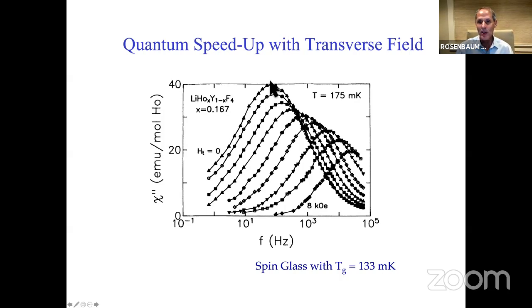Now, as I put on the transverse field, and this is 8 kilogauss of transverse field, the gamma and the Hamiltonian, which is in Kelvin, goes as the square of the applied transverse field of the lab. You see that the frequency response moves up and up in frequency. So the peak frequency here goes from maybe a little over 10 hertz up to a little over 10 to the 4th hertz.